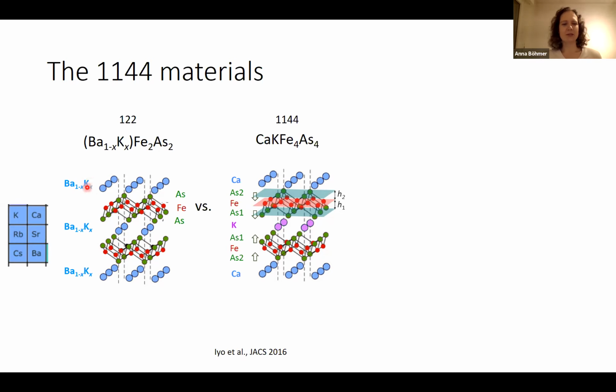So there is a mix of these two elements on the A site, and we have a doped 122 compound. On the other hand, and that was the discovery in 2016, some of these elements don't mix. When there's a size mismatch, they separate in layers. So we have alternating, say, calcium, potassium layers as one example. So this is not an alloy. This is really a 1144 compound.